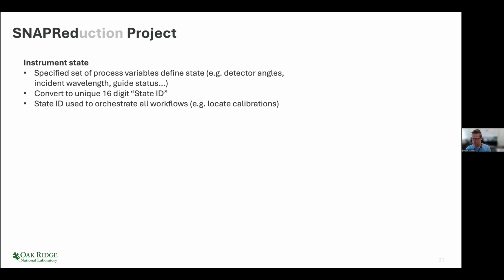And I won't spend too much time on it, but because it's been such an important part of my life for so long, I wanted to give a few details about how that actually works under the hood. We had to define the instrument state, which essentially we do by tracking the values of a specified set of process variables, which are things which are logged automatically whenever the neutron data are collected. Things like detector angles, where the incident wavelength band is centered, whether the guide is in the beam or not. These are all logged in the neutron data as process variable logs. And then we take the values of those logs and convert it to a simple 16-digit ID number. And then we create a folder with that same ID number. And that's used to orchestrate all the workflows. It allows the reduction to find the appropriate calibration data and to link it to the specific neutron data that's being reduced.